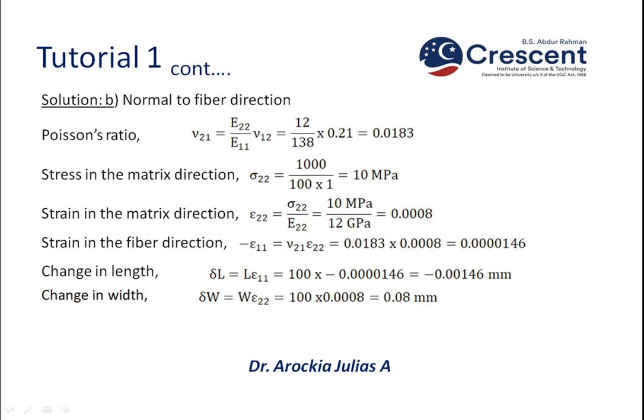Now strain in the matrix direction, epsilon 22 equal to sigma 22 by E22, Young's modulus 22. So again we are finding that as 0.0008. Now strain in the fiber direction. So here first we will find, because the load is in the matrix direction, the stress and strain in the matrix direction, that is the loading direction. Matrix direction is the loading direction for case B.